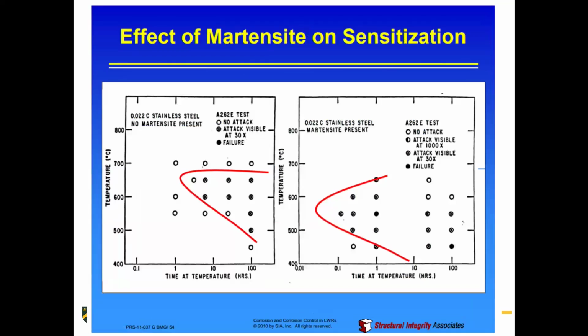So overall, this gives you a nice plot to show how much of an effect this makes. It can be pretty dramatic. Again, I think we're still dealing with 304. In this case, you're looking at martensite being not present versus present in this particular stainless steel. You can see that with no martensite present, your sensitization is pretty limited. But you have to hold it for a while, in terms of hours. So if you put that weld in place, unless the metal is staying hot for hours, you're probably okay.